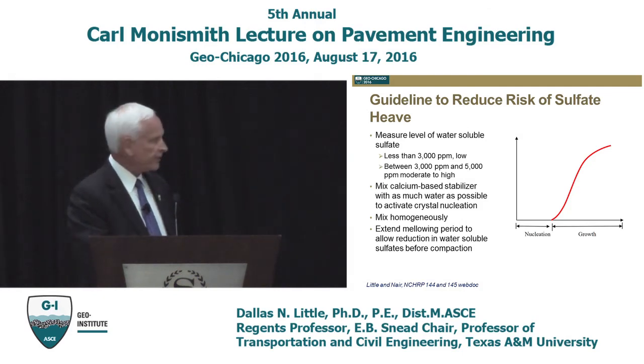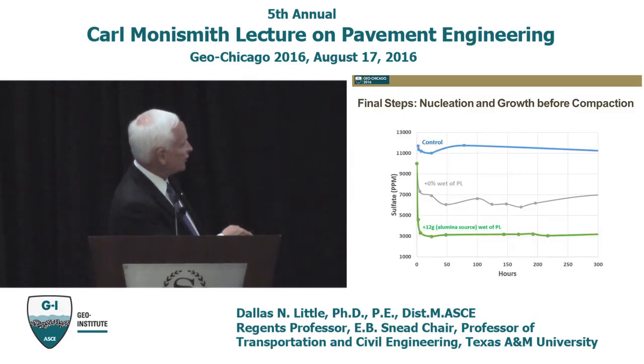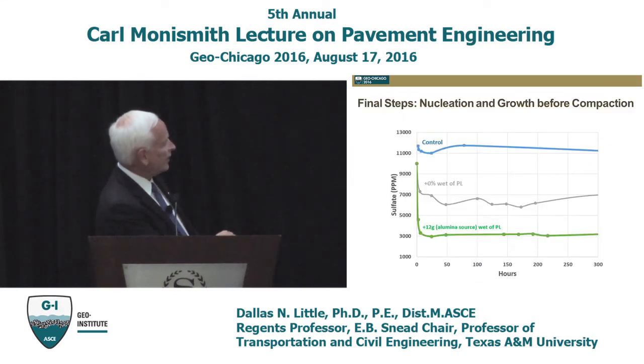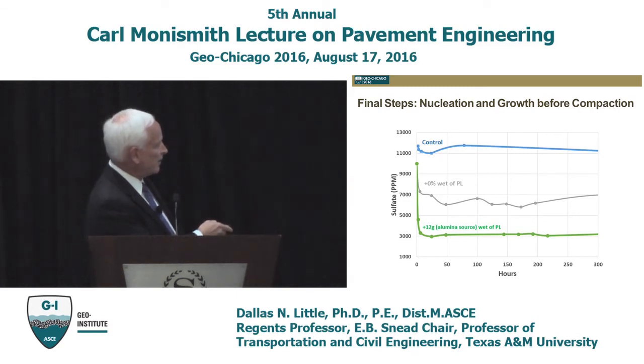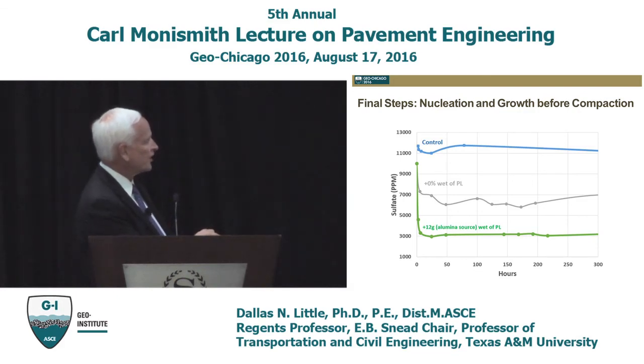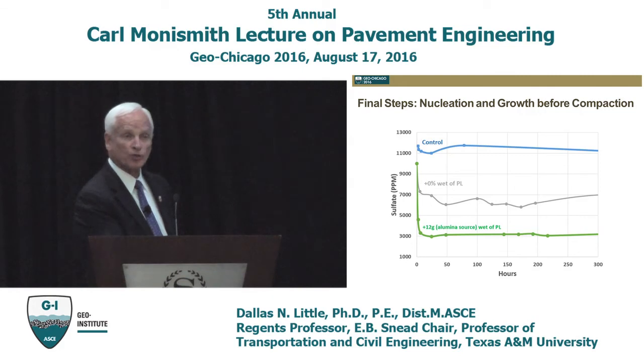One final point there that is quite interesting. This is water-soluble sulfate. This is hours. So if I start out with a control and it's dry, the soluble sulfates don't change. But if I get it a little above the plastic limit, and I'm adding lime to it, by the way, I didn't say that, the water-soluble sulfates is going to drop from a little over 1% down here to about a little over 0.5%. That's pretty good. But I can activate that process even more by adding an alumina source.